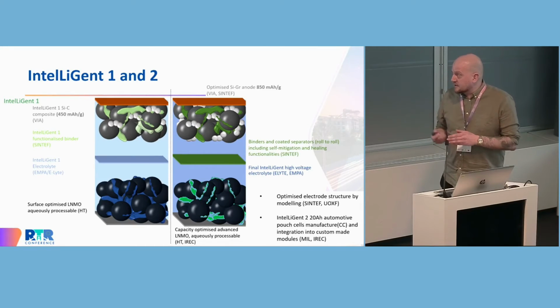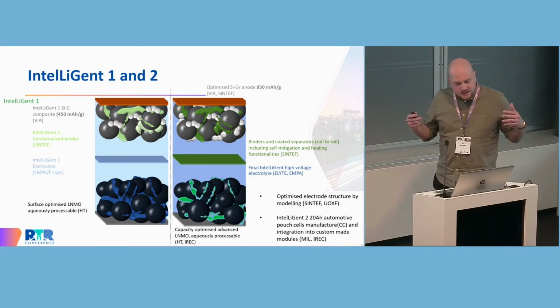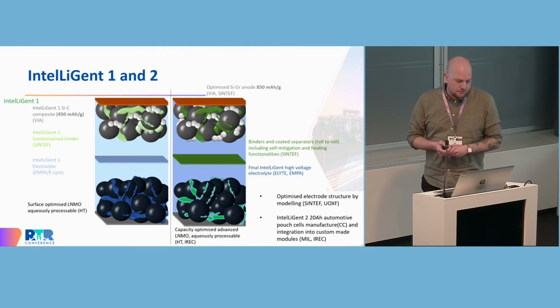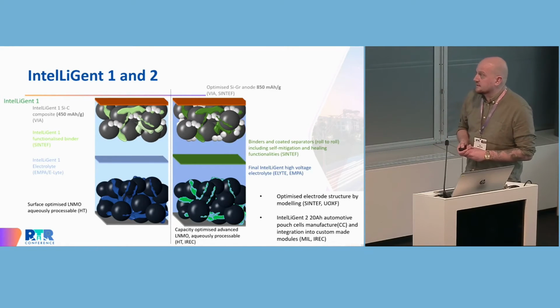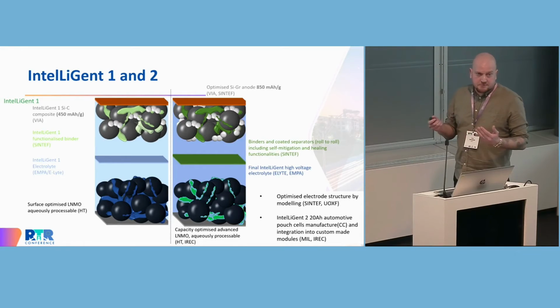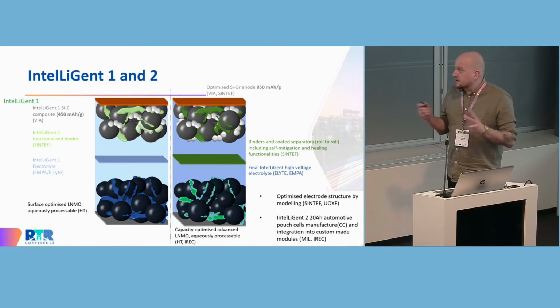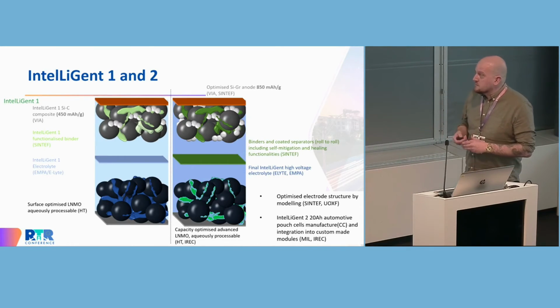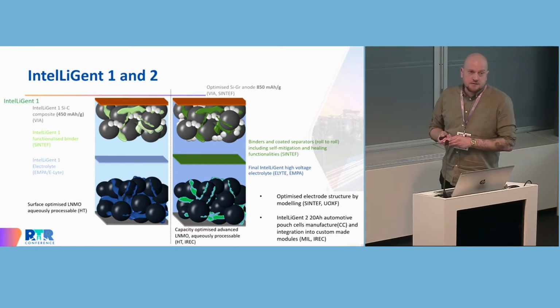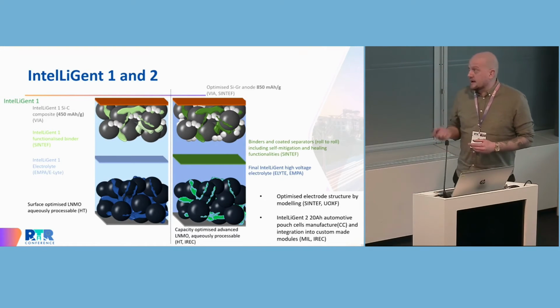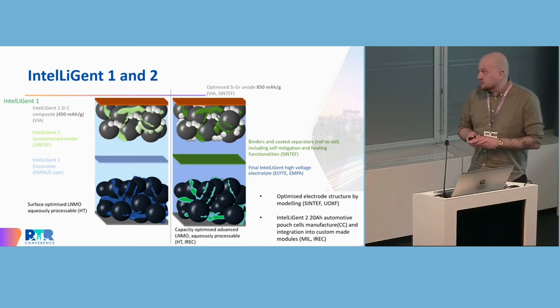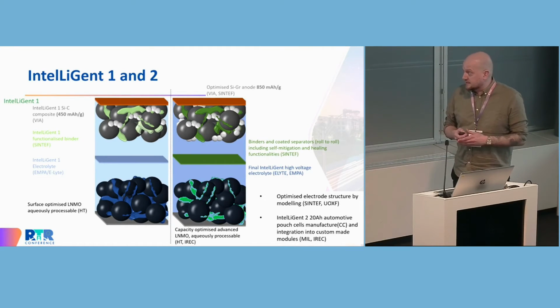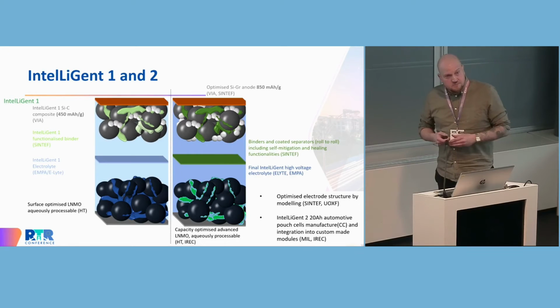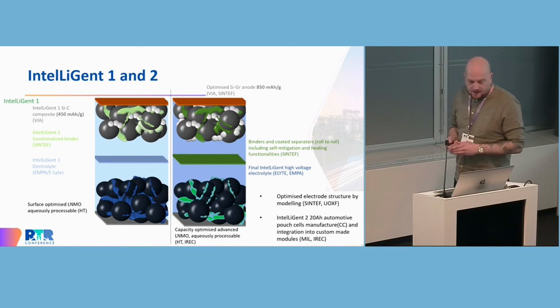We intend to have functionalities on the anode side so that the binder can actually interact and graft to the SEI of the battery, but also on the cathode side so that the binder is able to trap malign species, which sounds a bit so-so, but what we mean by this is that all transition metal oxide cathodes will leach transition metals over time, LNMO a lot, and these transition metals will interact with the SEI and will reduce cycle lifetime. We have learned that. So we would like to trap these transition metals in the cathode where they do not do any harm.